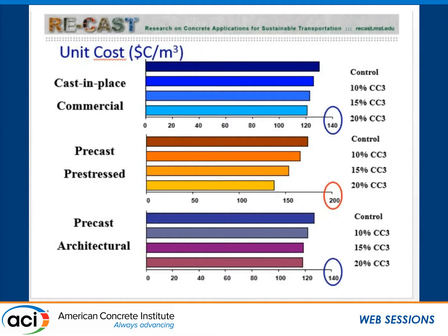But when you get into the precast application, because of that very, very sharp reduction in superplasticizer demand, that reflects also on the cost. And I must say also here we didn't have any VMA. And again, the precast application follows very much the superplasticizer demand. So what really is driving the cost over here is the superplasticizer demand. If you can get something that gives you a better packing density, lower water content or superplasticizer content, that would have that implication on the cost. So you can say over here, you can deduce for yourself that limestone filler that is finely ground is about the same cost as Portland cement. Yes, you're right. Not very different. As we go, it would be more cost effective. In this case, we are looking for high value added for specific applications, and that's for SCC mix designs.